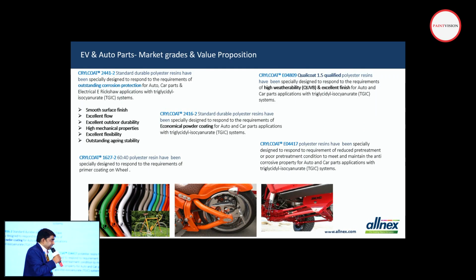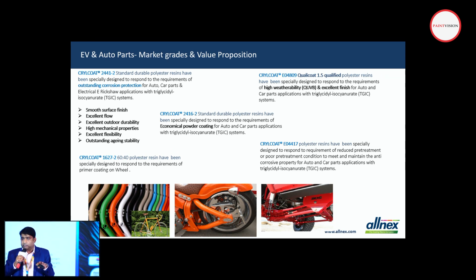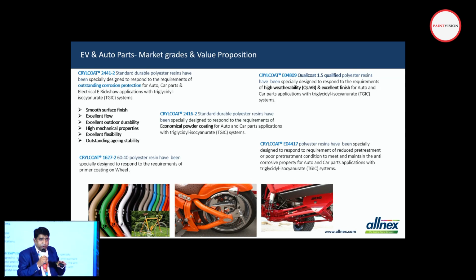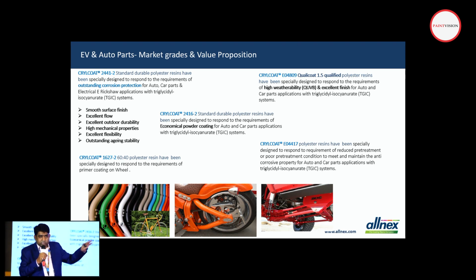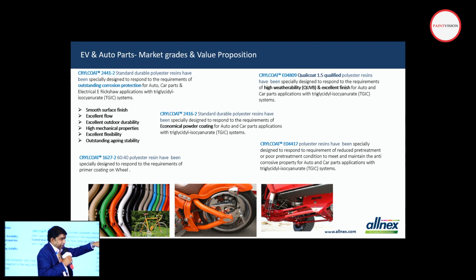Then we have 2416-2, and similarly for this market, especially for e-rickshaw segments, because there we feel that the pre-treatment of the substrate is not good enough, especially in this unorganized or semi-organized market segment of electrical rickshaws, or e-rickshaws as we call them. So we have designed a polyester resin, Crylcoat E04417, which meets the requirement of corrosion resistance even on poor surface treatment. This is one of the new grades in terms of surface treatment. If poor surface treatment is there, we still use this grade and get excellent corrosion resistance and adhesion.